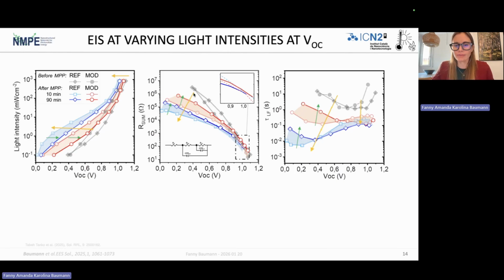In our case, we're going to see 3 major changes, and we are going to see how they are slightly different from the reference and the modification. So in the first case, we have voltage losses, especially at lower light intensities. Second, we have a lower shunt resistance that is showing up here, and this is also a voltage-dependent shunt resistance that we're calling a Perovskite shunt resistance. You can read more about this in this paper.